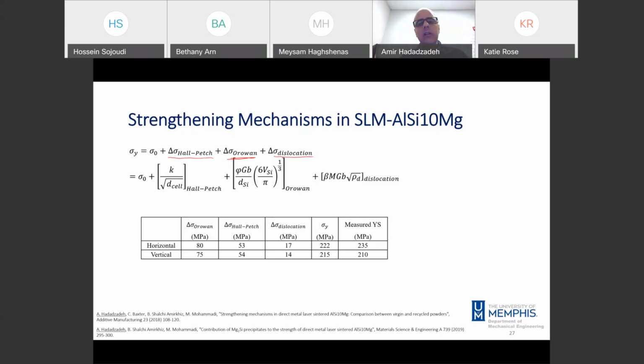Considering that, I don't want to go through all the details of the math here. I was able to predict the yield strength. Also, I measured the yield strength through the experiments, and there is a very good agreement between the measured values and the calculated ones, specifically for the case of the vertical alloy. As you see, 215 was predicted, and the measured value was 210 MPa, pretty close. But there is a slight difference between the yield strength in the case of the horizontal sample.